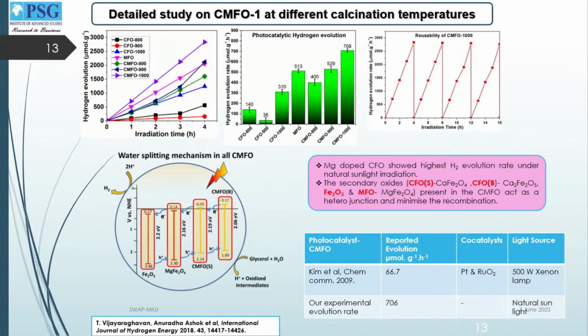So when we conducted the hydrogen generation experiment on all these composites, we could see that the one with multiple phases was more effective in water splitting compared to the phase pure or more phase pure mixture. The reason we gave was the larger recombination time. So the electrons and holes have been effectively separated so that they participate in splitting of water.